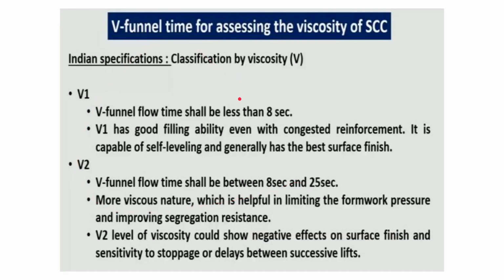Based on the viscosity timing, the Indian specification can classify two types of SCC. If the V1 time is less than 8 seconds, that means it has a very good filling ability, because it can move quite fast. The viscosity is not that high, the flowing ability is quite high. So it has good filling ability even with congested reinforcement, and it can be used where the density of reinforcement is high. It is capable of self-leveling and generally has the best surface finish, so it is of superior quality concrete.